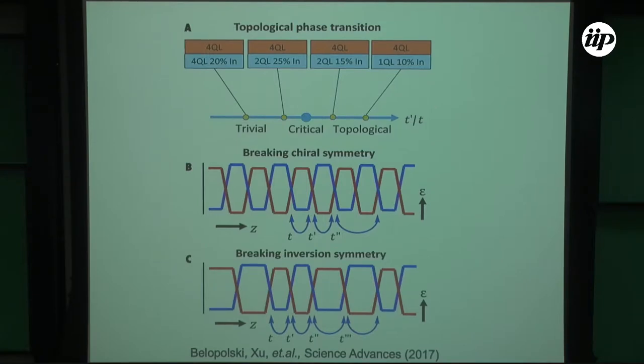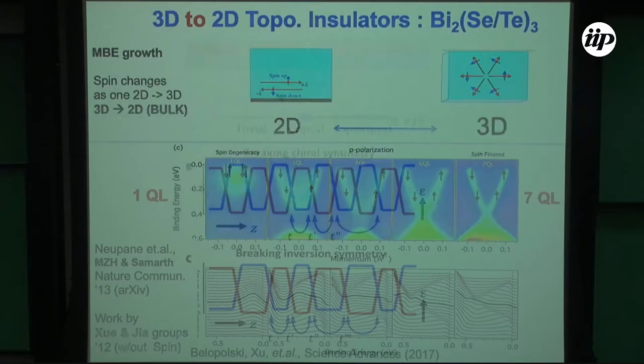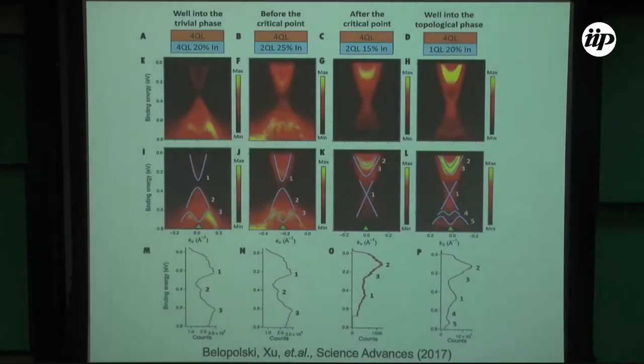So without thinking much, without the multilayer effect, you would think that if I do ARPES on all these samples, I should see the same thing, because ARPES is just seeing the surface. Or I can make ARPES see the surface only. So then you would see that there is no way for us to tell whether there is a topological phase transition or not if I just do ARPES. But now imagine this case, that when we enter this regime, then I have a system that is globally topological now.